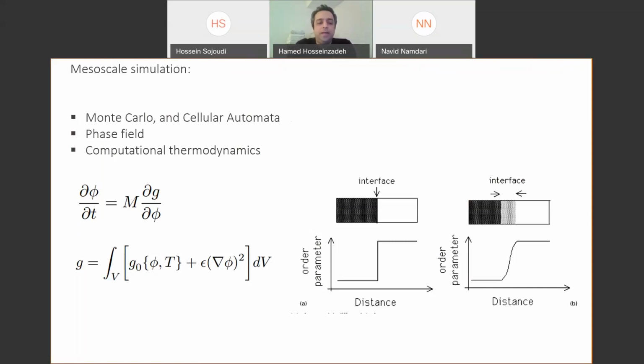We have an order parameter, and we develop the energy of the system based on the value of the order parameter and the slope of the order parameter. We define the energy of the system and put in the equation, time-dependent equation. You can see that. So we minimize the energy for the order parameter, and we can capture the movement of the order parameter. Order parameter is working as interface in this. So, for example, if you have a polygrain system, you want to see the grain growth. The order parameter is the grain boundary of the system.